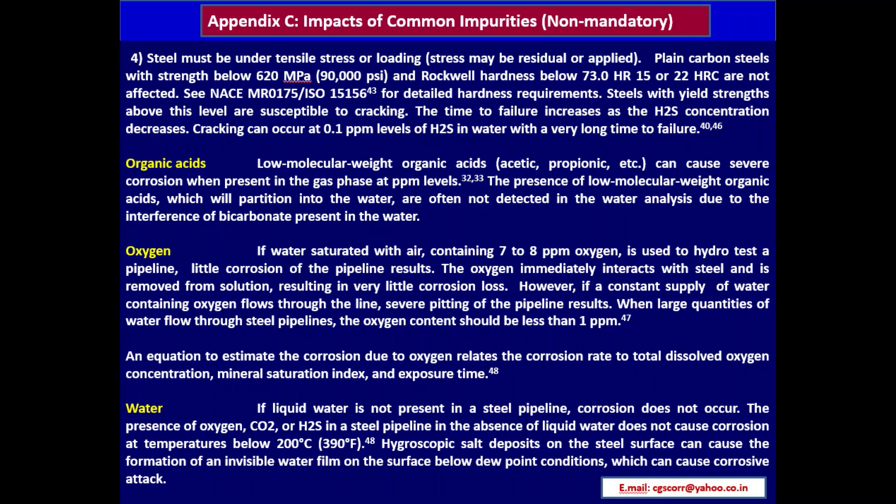Water: if liquid water is not present in a steel pipeline, corrosion does not occur. The presence of oxygen, carbon dioxide, and hydrogen sulfide in the absence of liquid water does not cause corrosion at temperatures below 200°C (390°F). However, hygroscopic salt deposits on the steel surface can cause formation of invisible water film corrosion on the surface below dew point conditions, which can cause corrosive attack.